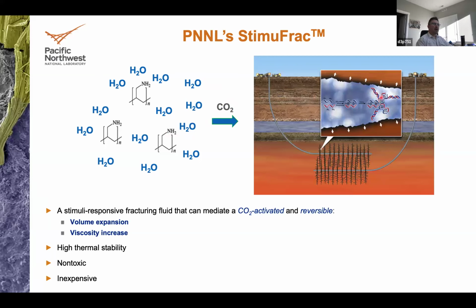And this fluid expands in volume and also increases viscosity. The beauty of this is not only that, but also that the reaction is reversible. You can depressurize, with the CO2 pressure removed, and you get back to a solution of the polymer which you can recover with the produced waters, as well as the CO2 also recovered and repressurizing in the next wellbore. So reversible volume expansion, reversible viscosity increase, and we will talk about how each of them may help aid the efficient fracturing of rock at geothermal conditions.